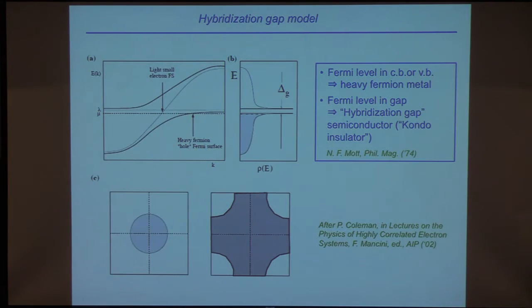And here's one way in which you can kind of visualize how you can get this heavy fermion state. So this is based upon an idea due to Neville Mott back in 1974. So this is energy versus K, so you have a broad, say, SP band right here, and then an F level or narrow F band crossing, intersecting this band right here. And so the bands will hybridize and repel each other, and so you're left with a small gap. And then, depending upon where the Fermi level is, you can get a heavy fermion hole-like metal or electron-like metal, say if it lies up here.